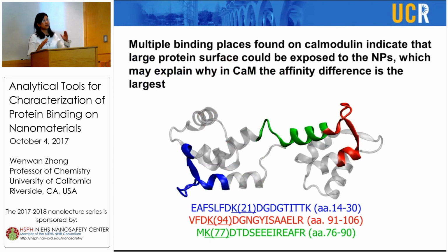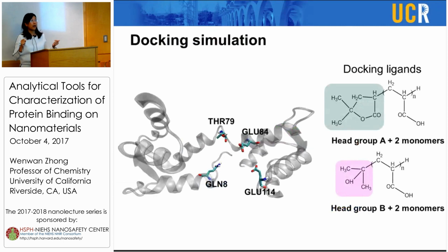So what we think is that the reason the surface group can be so important, although it's just a head group difference, and it affects the binding so largely, is because there is a large interaction interface formed between the protein and the nanoparticle. So a small change in the localized interaction strengths actually contributes to the overall affinity differences. Therefore, we asked our colleagues to help us do computer simulation, which indeed found that if we do docking,